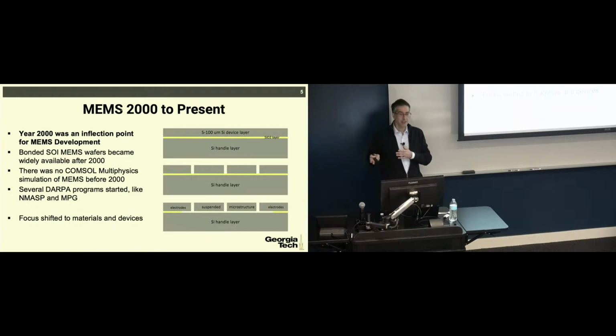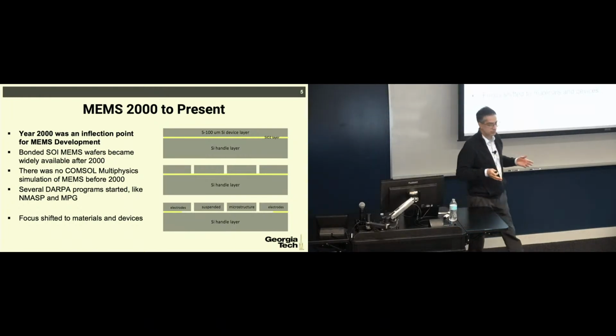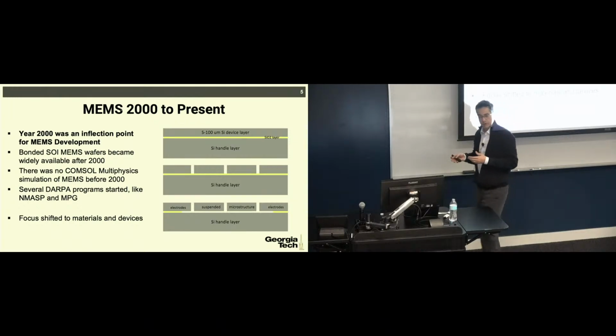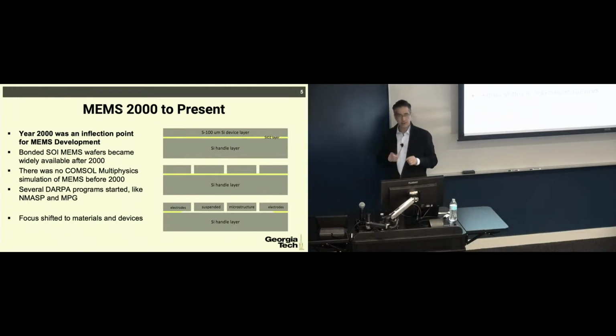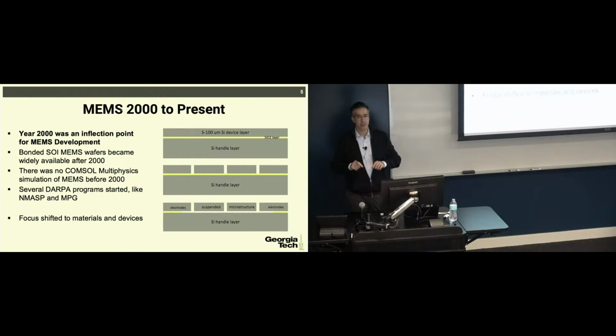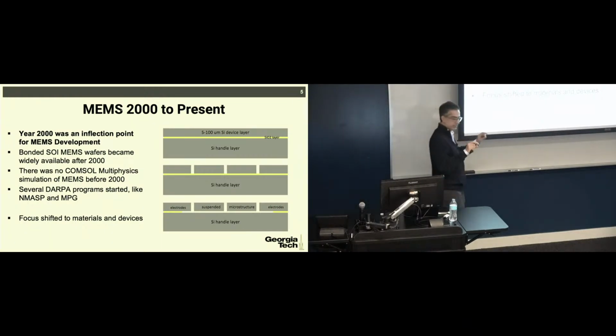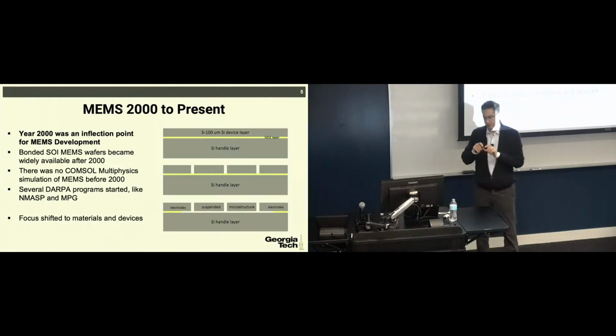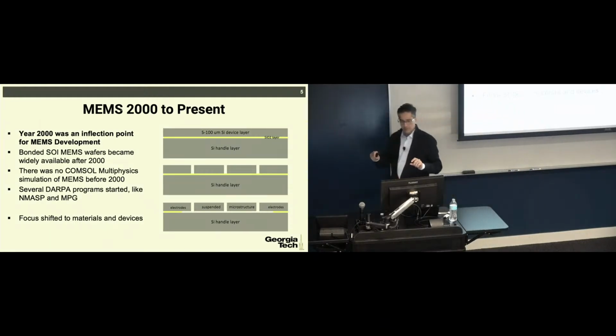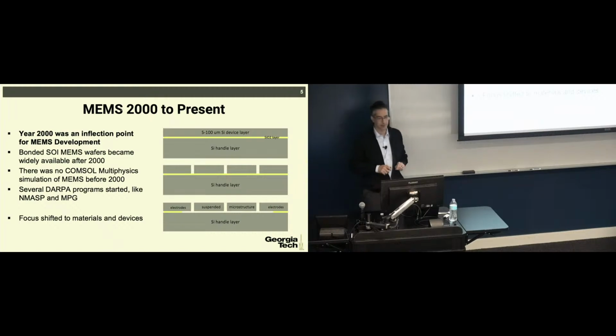So the silicon on insulator wafers were available before that for CMOS processing through a process called SiMOX, which is implanting oxygen into the silicon and creating a very thin layer of silicon to create transistors on top, and then isolated from the rest of the substrate through this oxide layer. But as I said, the thickness of the silicon would be limited through a SiMOX process.